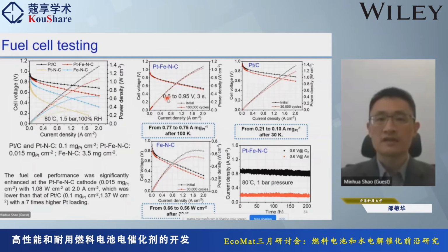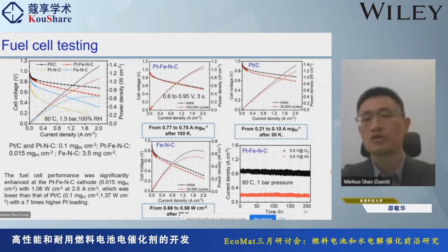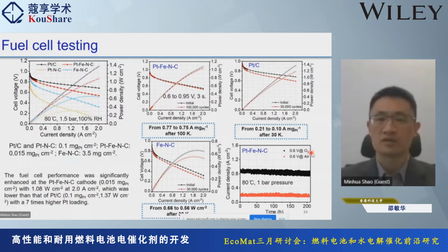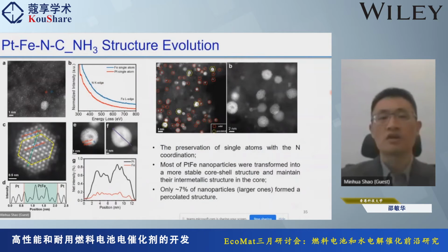But the most interesting thing is that after 100,000 cycles, the hybrid catalyst does not show any decay. For the platinum, only after 30,000, you can see the decay is already significant. The mass activity already dropped by 50% after 30,000, and for the iron nitrogen, after 30,000, the power density also dropped significantly. And for the hybrid, if you keep the same potential, the current density does not show any decay. After 200 hours, we could do this much longer, but we actually stopped the testing. So this is the first time that we demonstrated that not only the mass activity but also the durability can be significantly improved for this non-precious metal.